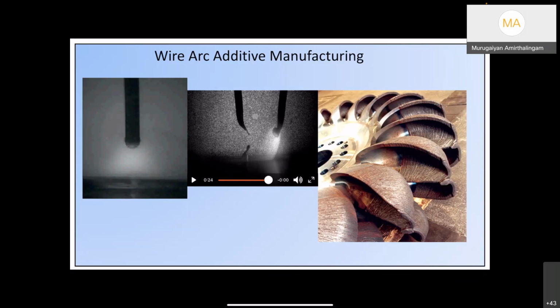There are other advantages in this technique. For example, here I showed two wires, isn't it? So we have a tandem wire over here. These wires are deposited simultaneously, and we can also increase the productivity by using a process like a tandem wire. And we can also locally change the composition of the pool if we use a different wire by controlling the melting rates. The classical example I showed here is a component where the inside, the rotor, should have, in this application, good rolling contact fatigue and good toughness and strength to meet the load. These impeller arms are actually reacting with the fluid. If it is in seabed or sea applications, these impeller arms are exposed to a high corrosion environment, so it should have very good corrosion resistance.